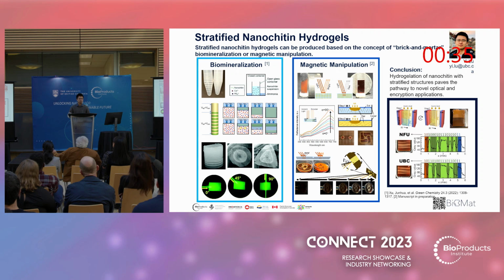For example, we do the in situ biomineralization by co-precipitating with the calcium apatite. As such, you can get this layer by layer structures that have very interesting optical performance. Also, we can use the magnetic manipulation where we use the hydrogel framework to fix the iron decorated nanochitin. And we can actually create those barcode-like structures that encrypt certain messages, like the pattern of UPC in our hydrogel.